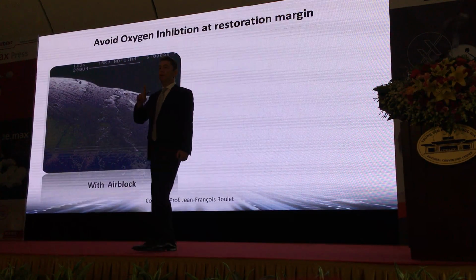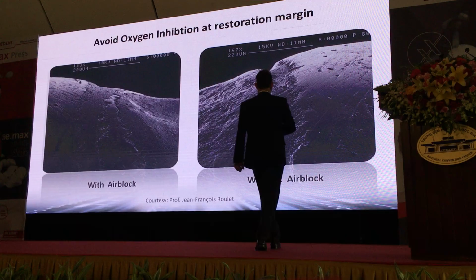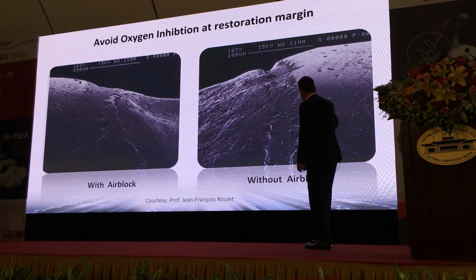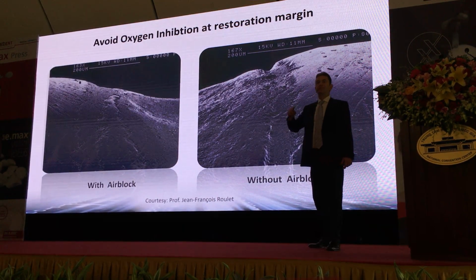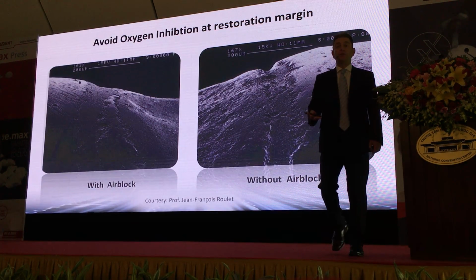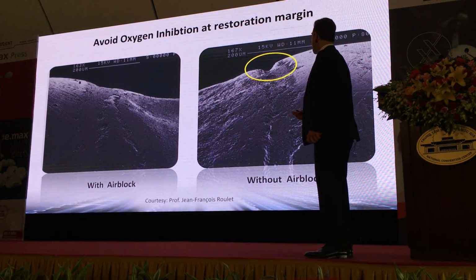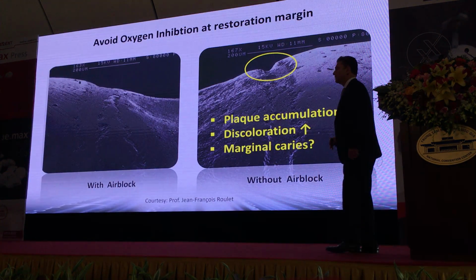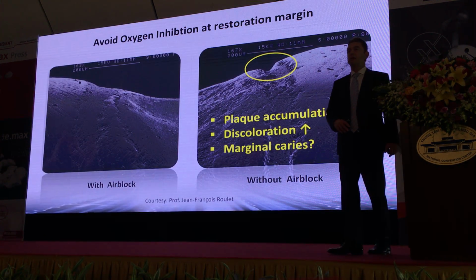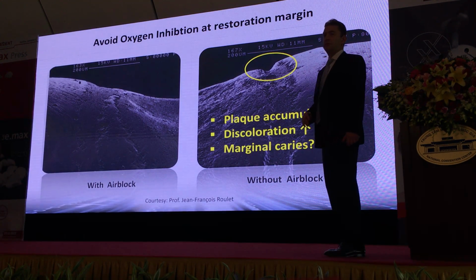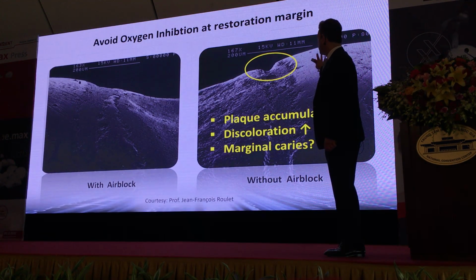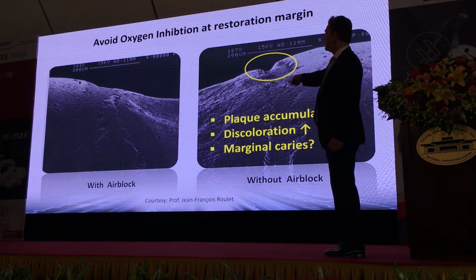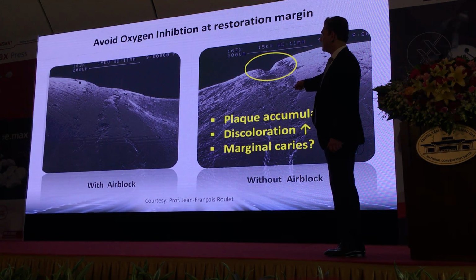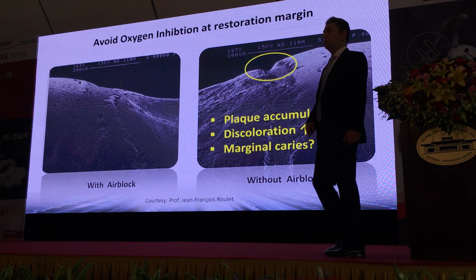If you do not do this, you have something like this. Because here the cement line is not completely cured, so it will wear off. You have a catch. And that's very bad, because you have a rough surface, so you might have more plaque accumulation, more discoloration, and maybe also more caries. Maybe. So I would like to avoid this, and I rather want to achieve this result here. And it's very easy to do.